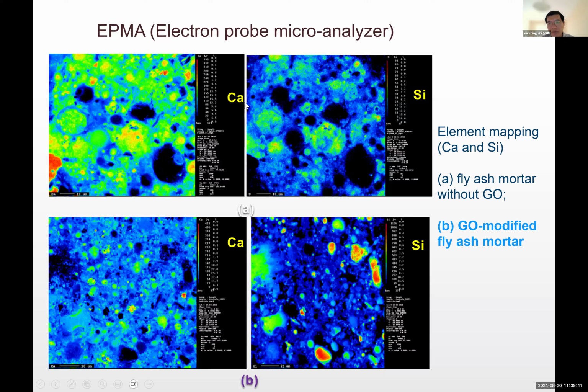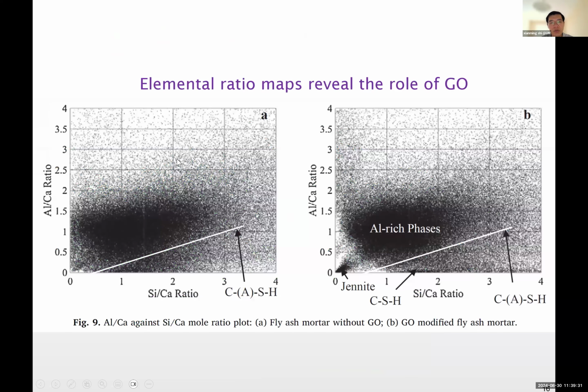So you can do color mapping of the elements, which is very visual, or you can do the elemental ratio by dividing calcium by silica. Then you can create another sort of map. So again, visually, you can see some difference between the top one, without graphene oxide, and the bottom one with graphene oxide. But there are other ways. For instance, quantitatively, like I mentioned, we have tens of thousands of data points. Then you can calculate the aluminum to calcium ratio as a y-axis, and silica to calcium ratio as an x-axis. Then you start seeing some patterns.